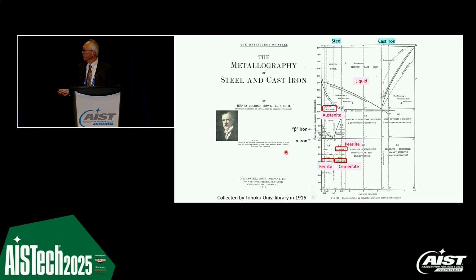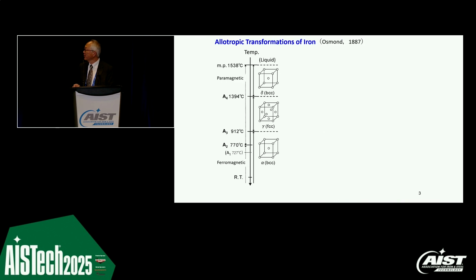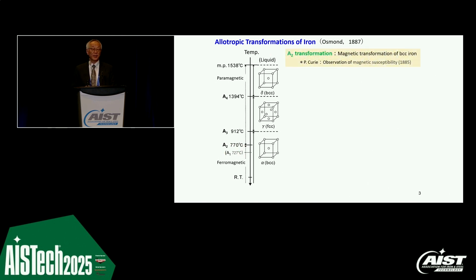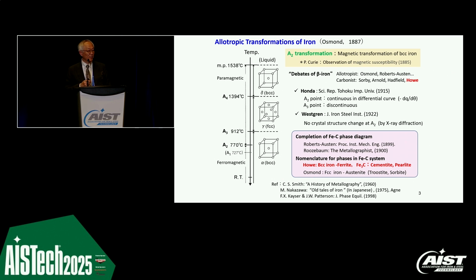Here is the iron-carbon phase diagram, and we all know the nomenclature of all the phases in the phase diagram, but this is Professor Howe's work, one of the best work in his career. And of course, you know the phase transformation in solid state in iron after cooling down from the melting temperature: BCC, FCC, and again BCC. And there is one transition temperature, the so-called A2 temperature, that is the magnetic transition for pure iron. There was a debate about so-called beta iron. In the previous phase diagram, there was a region for beta iron and alpha iron for BCC.